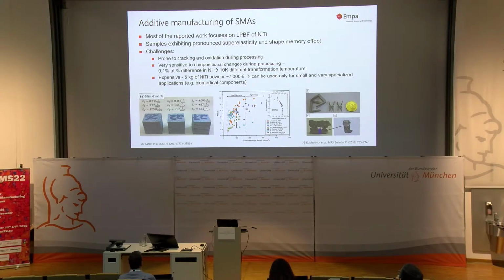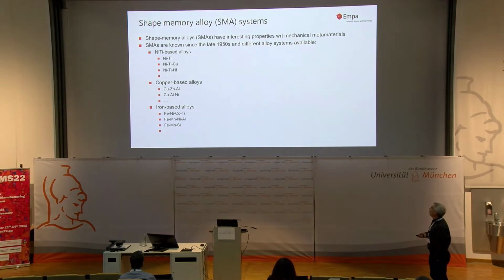So here's the study: volumetric energy density, and here is finally the transformation temperature. You can see it's difficult to really tailor the properties of the shape memory alloys. But one of the biggest challenges here is the price. It's rather expensive. This number I know because I ordered that powder, 5 kilos, for around 7,000 euros. Therefore it's used mainly for rather small and very specialized applications, mainly for biomedical components, as these examples show.